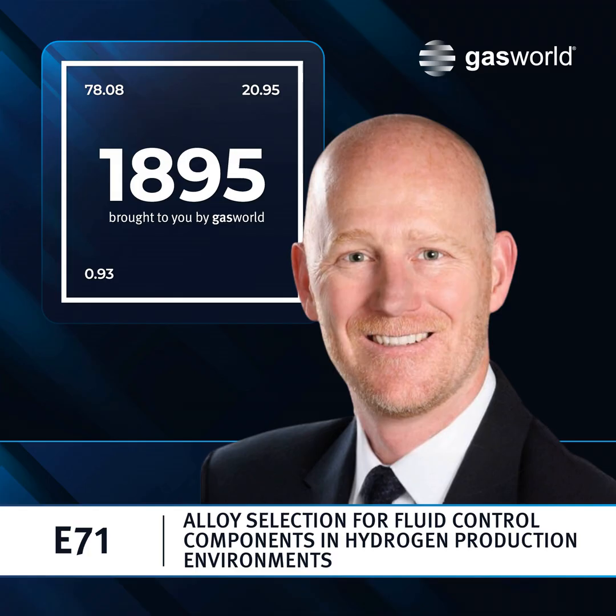In a few cases where the caustic environment is more concentrated, such as in the lye feed system, and particularly if it's being done at a high temperature, Monel, or a nickel copper alloy, also referred to as alloy 400, can be an appropriate choice, but really not needed very often, really special cases to be considered in each different application.